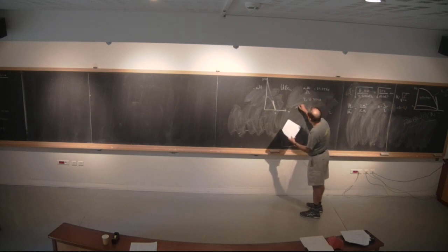Okay? But anyway, so in this system, mu naught dHc by dTc is 25.7 Tesla per Kelvin. Tc is 0.925 Kelvin, and therefore mu naught Tc dHc2 by dTc is 23.8 Tesla. I guess that should be 23.8. Extrapolation there, okay? Which is a huge number for a 1 Kelvin superconductor, okay?